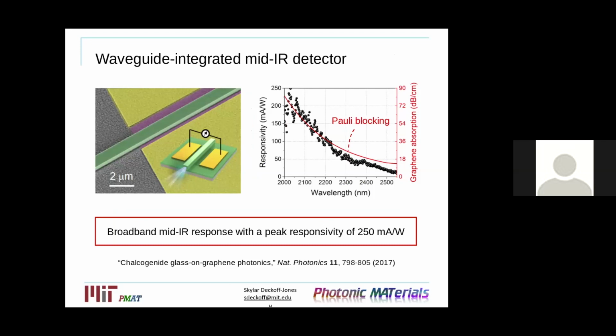Additionally, we fabricated a mid-infrared photodetector where we had a photovoltaic detection response, and we see very high responsivities over a large bandwidth, where we see a decreasing responsivity which can be attributed to Pauli blocking, where the longer wavelengths no longer have sufficiently large energies relative to the position of the Fermi level of the graphene.